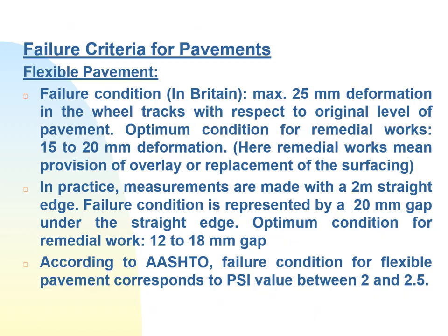Now at the end, we will focus on the failure criteria for pavement. For flexible pavement, first look at the failure criteria. Failure condition in Britain: maximum 25 mm deformation in the wheel tracks with respect to the original level of pavement. Optimum condition for remedial works: 15 to 20 mm deformation. Here, remedial works means provision of overlay or replacement of the surfacing.